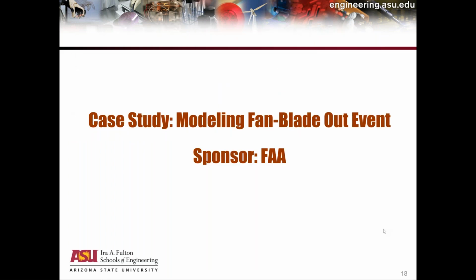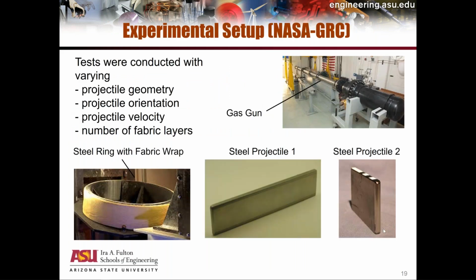So there are 4 case studies. I'll quickly go through the first one, which deals with the engine containment system. Most of the testing, high velocity impact testing, was done at NASA Glenn Research Center. You can see the gas gun on the top right. And we have a 40-inch diameter steel ring wrapped with layers and layers of Kevlar. There is a cutout here where these 2 projectiles are going to hit the cutout. So in other words, these projectiles are going to hit against the Kevlar layers.